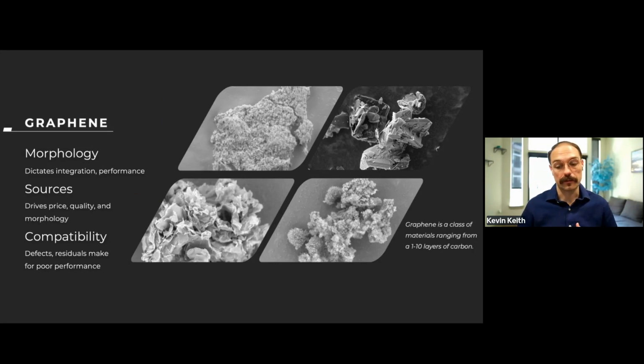So graphene, I hope everybody is aware, is a family of materials. The ISO standards that are going into effect hopefully next month are going to qualify this as graphene-related 2D materials, or GR2Ms. Graphene has a lot of different buckets for characteristics. Mainly, graphene is considered graphene when you have anywhere between 1 and 10 layers of carbon stacked together. And these SEM images are all different types of graphene, made from different manufacturing methods, exfoliation processes, and chemical methods. So morphology, a lot of the time, dictates the integration and performance of this particle, as well as the system that you put it into, whether that's based on mechanicals, thermal, electrical, which then stem into other applications. For the sources, you can go from graphite down to graphene, or you can even go from a waste gas into graphene, and I'll get into that a little bit later.